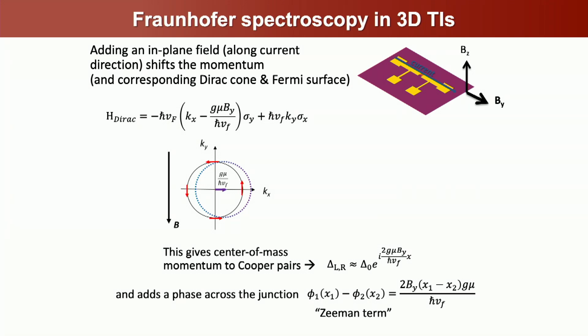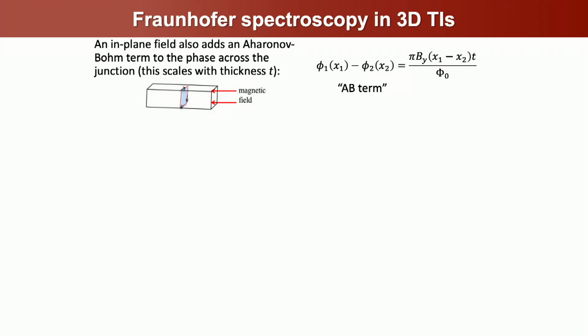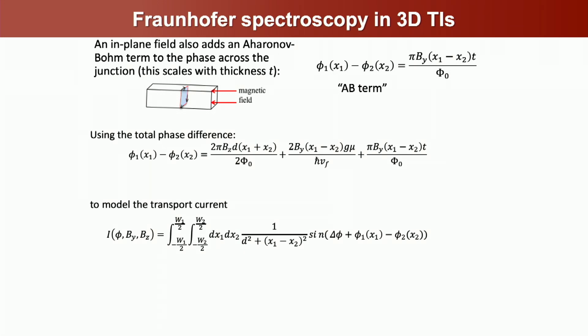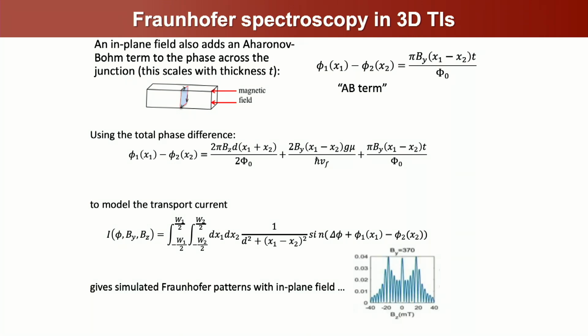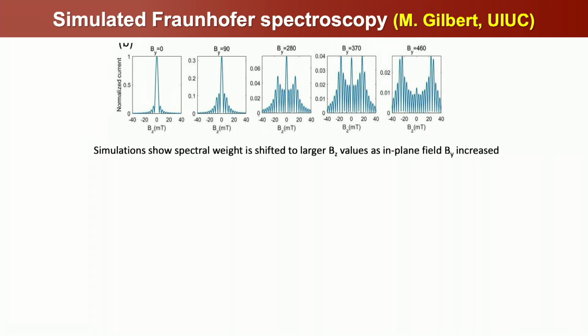We should also see an Aharonov-Bohm term because we're putting a field in along the current wire. So we get a Zeeman term, an Aharonov-Bohm term, and the standard single slit diffraction term, and we can model the transport current in this case and see that we get simulated Fraunhofer patterns where the spectral weight is shifted to larger values of field in the case of this finite momentum shifted states.